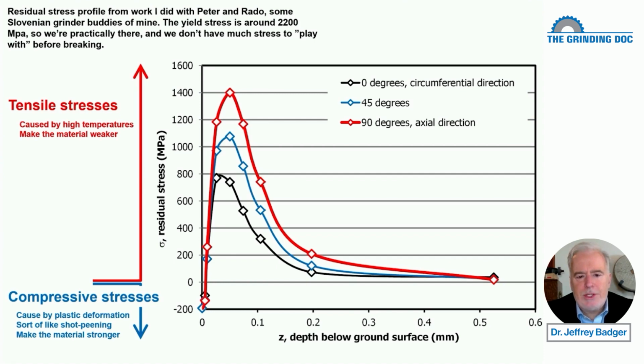So this is a residual stress profile. Now, residual stresses begin to occur when things get hot in the workpiece. It's this funky reaction where the workpiece wants to expand because it gets hot, but it's restricted by the surrounding material. And if the expansion it wants exceeds the yield stress, then we get permanent plastic deformation in compression. Then when the cooling comes and it shrinks, wanting to be smaller, it's in a state of tension. I don't expect you to remember all that because it's complicated, and I talk about it in the book of grinding in more detail.